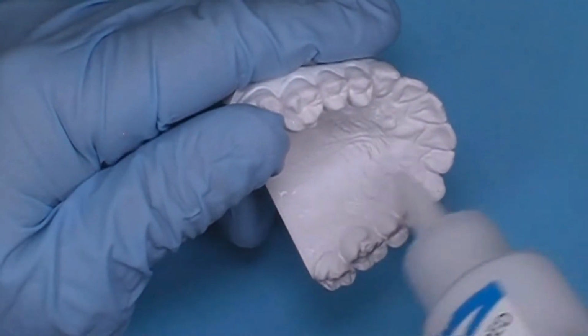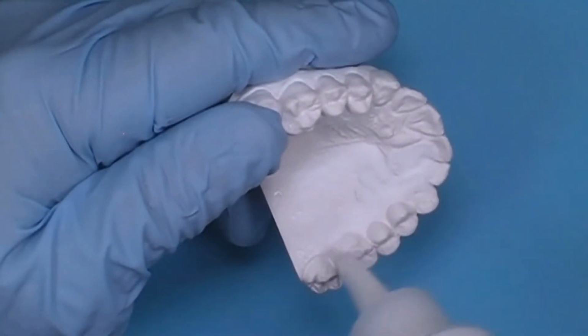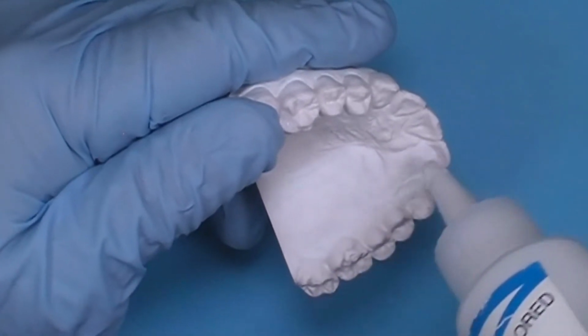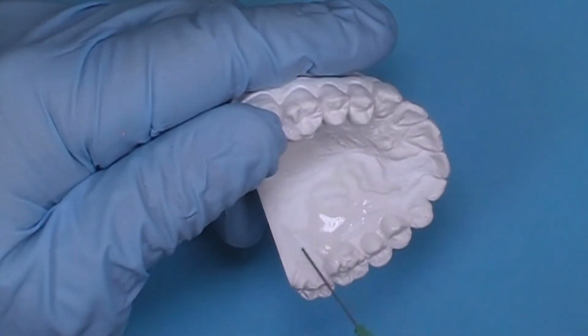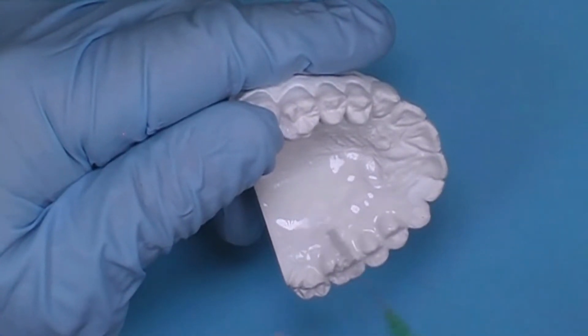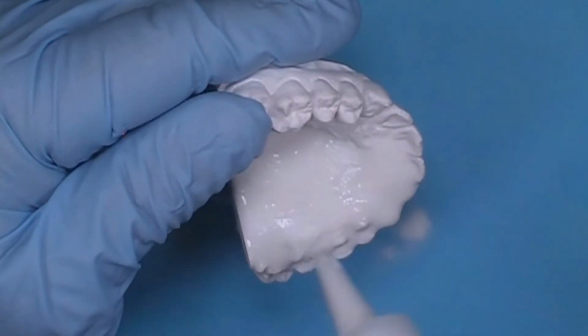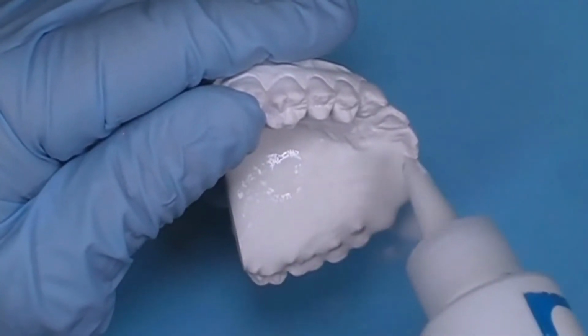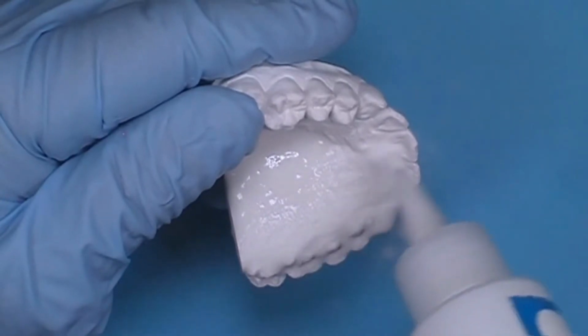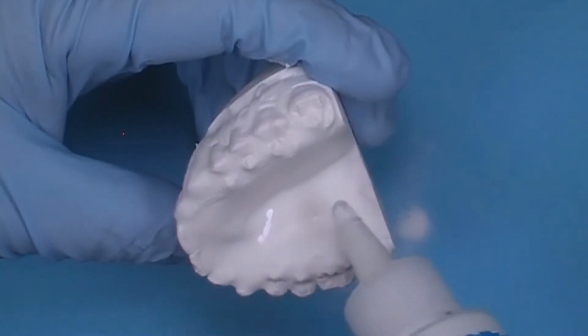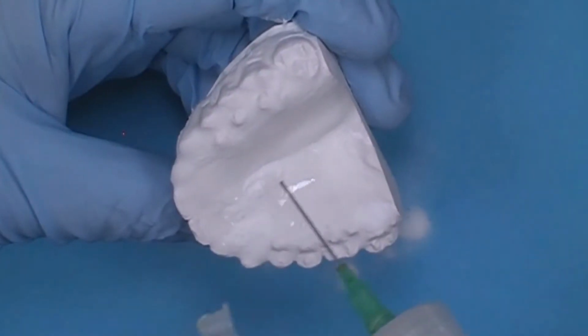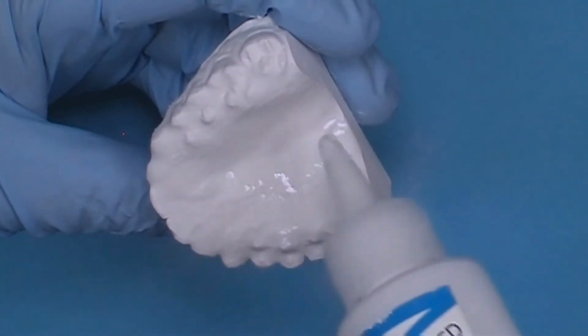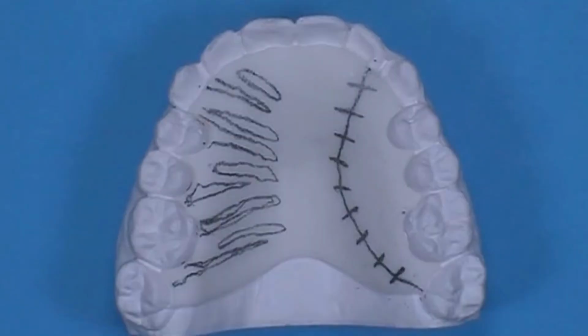With Great Lakes separator applied to the model, Snow White contemporary polymer with clear biacryl monomer is used to make an acrylic base plate. The salt and pepper technique, applying polymer and monomer layers, is used to build each side of the arch to desired thickness. Each side is completed with a dust of polymer, then placed into a Great Lakes humid pressure pot to cure for 15 minutes. Once cured, the acrylic is trimmed and sanded smooth.